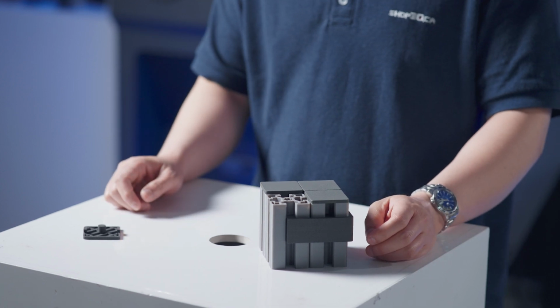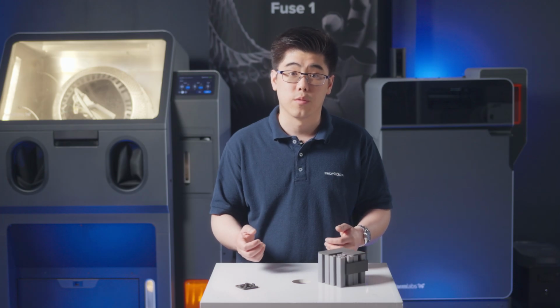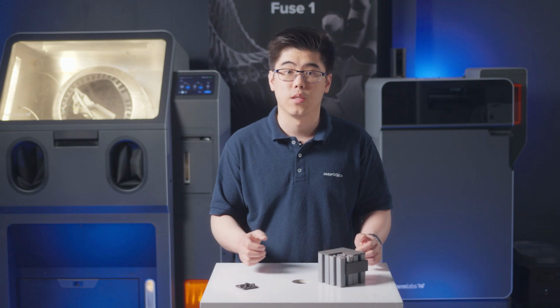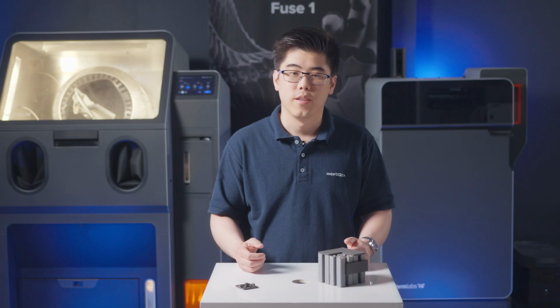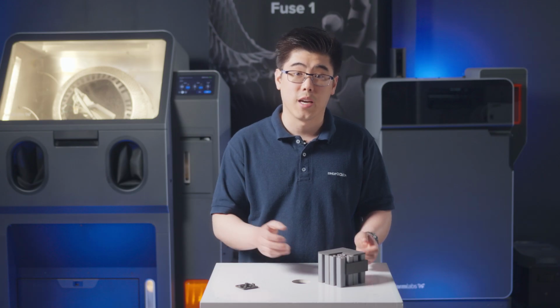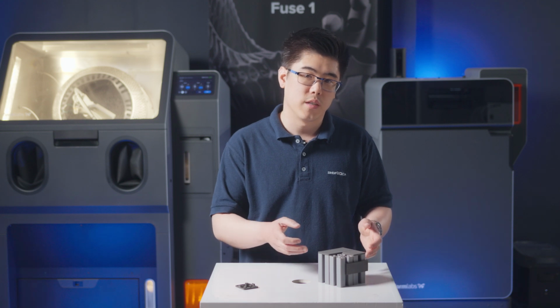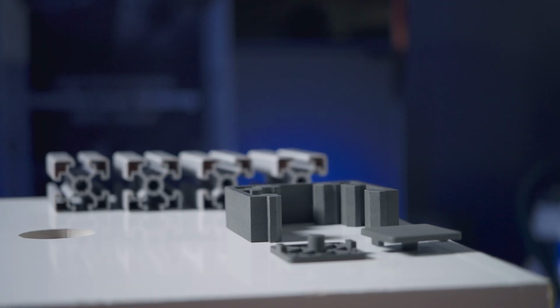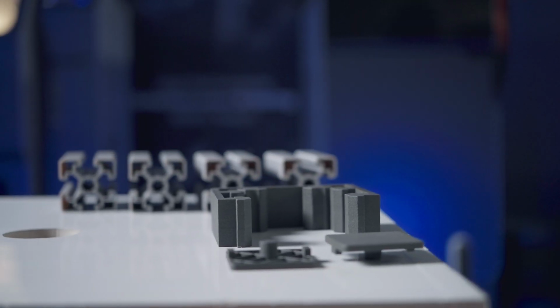To produce all 110 pieces took about 3 kilograms of powder, with about 1.4 kilograms of powder being sintered to produce the parts themselves. The remaining 1.6 kilograms of powder can be reused, and with nylon 12's 30% refresh rate, 70% of the powder used for a print job can be this recycled powder. In all, the total powder cost for the end caps is less than $1, and for the jig, a little over 10. The Fuse 1 is a great choice for something like these for a couple of main factors.